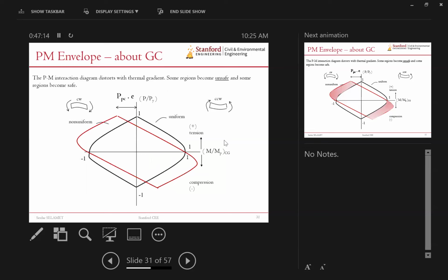So this black PM envelope is the one that's at ambient temperature, or any temperature that's uniform. It could be 400, 500, because you can see it's normalized. So it will always stay in the same shape if we have uniform temperatures. But if you have a non-uniform temperature, you have this extra moment that's being induced in the structure. So this envelope, which you see in red, will actually shift, or we call it distortion of the envelope.